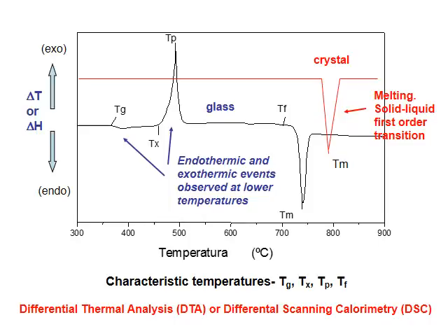Next, you keep heating your supercooled liquid. Viscosity will decrease with the increase in temperature, and at a certain temperature, atoms will have enough mobility to go to the most stable thermodynamic phase at that temperature, the crystal. At the temperature denoted Tx in the figure, glass starts to crystallize. Above that temperature, what you have in your crucible are crystals. Crystals that will start to melt at Tf temperature. This peak of the endothermic melting event is called the melting temperature, or Tm.